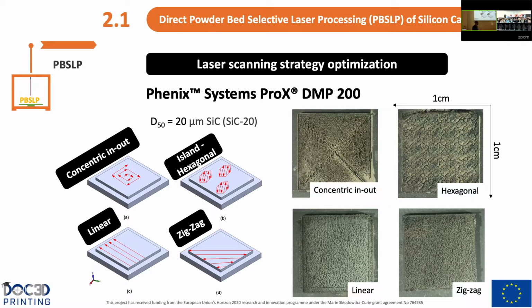Next, in the zigzag strategy, we are avoiding these problems, but we still have some defects in the corners due to the very short scan lengths of the laser, with a lot of heat concentration and the creation of some decomposition. And finally, we have the hexagonal, which avoids all the problems that we have mentioned, and it seems to be the best one.